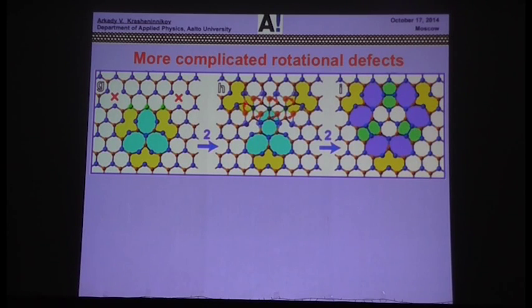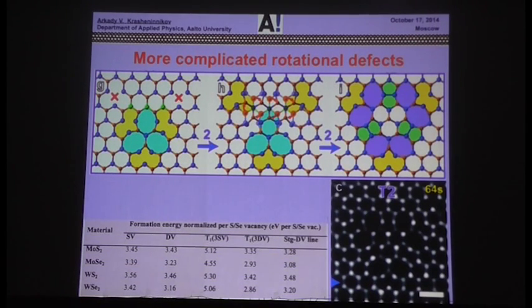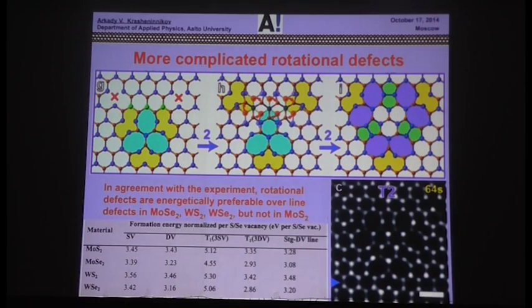And in fact, you can consider this process, do more transformations, get other more complicated defects, and the process can be continued. What's interesting, if you compare energetics of line defects and these rotational defects, rotational defects will have lower energy in tungsten disulfide, tungsten diselenide, and moly diselenide, but not in moly disulfide. And exactly this is what experimentalists see in real life. In moly disulfide, they have line defects, while rotational defects appear in other materials.